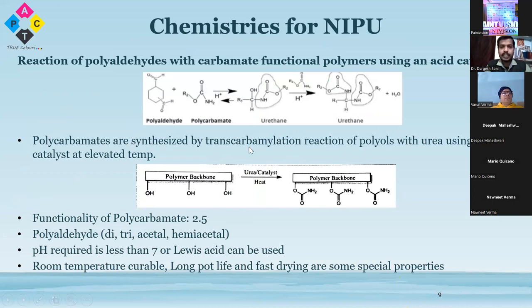with urea using a catalyst at a high temperature. So the functionality of polycarbamate may be greater than 2, like 2.5, and polyaldehydes may be di, tri, acetal or hemiacetal. Also, Lewis acid can be used, and it is to be performed in an acidic medium. This has the advantage that it is room temperature curable, it has a long pot life, and very fast drying properties are available in this.